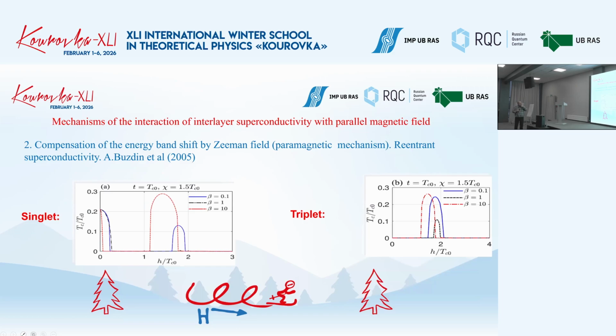The next thing which is important is the following. It's compensation of the energy band shift by the Zeeman field. This story was first discussed by Buzdin with co-authors 20 years ago. And what is the idea? Look, you have some splitting of the energy bands because of the energy band offset. If you now split the levels in each film by the spin splitting because of the magnetic field, you can have some levels coming closer to each other.